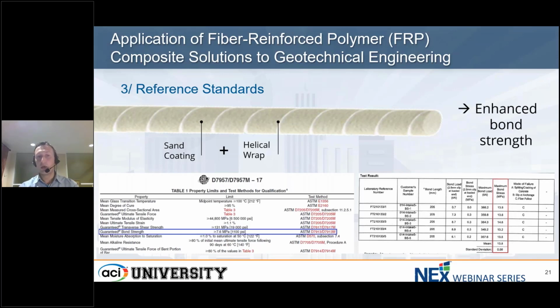Typically, one way FRP bars can transfer the load to the surrounding material is through surface deformation or enhancement. A typical geometry used is to have sand coating and/or helical wrap. That's why we can ensure we exceed the requirement of ASTM 7957 as far as bond strength is concerned. These kinds of properties will be a great help when it comes to designing ground anchors.